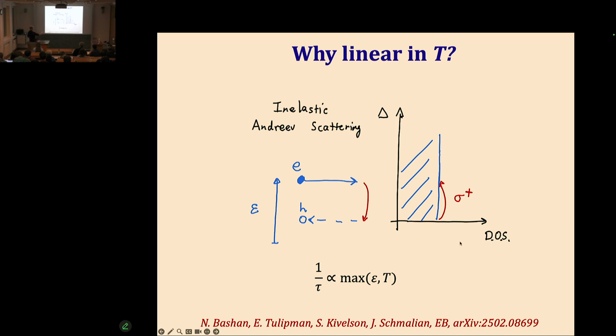The first one is what actually guarantees that this density of states of low energy excitations of the islands is constant all the way down to low energy. It turns out that that's charge conservation. This is where the fact that it's actually superconducting islands matters, that these two levels, the ground state and the excited state of the two-level system, actually have a different charge.